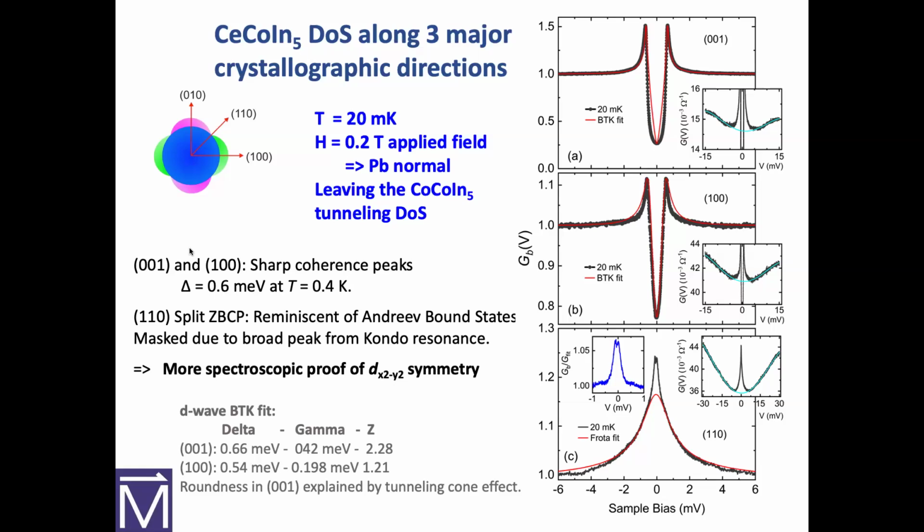Remember we talked about Andreev reflection: you send an electron in, let's assume there's no momentum difference or anything, and two electrons come out. The proximity effect is that if you look at the probability of finding Cooper pairs on the superconducting side and the normal side, in the normal metal you're not going to find Cooper pairs. In the bulk of the superconductor, you find Cooper pairs. In between, there's a drop off. That's the proximity effect.